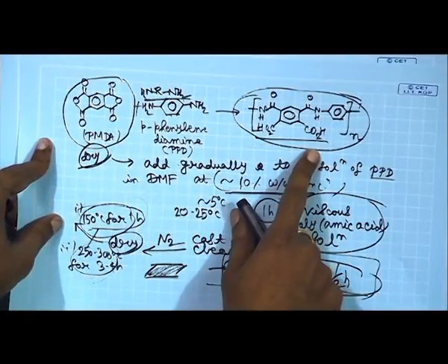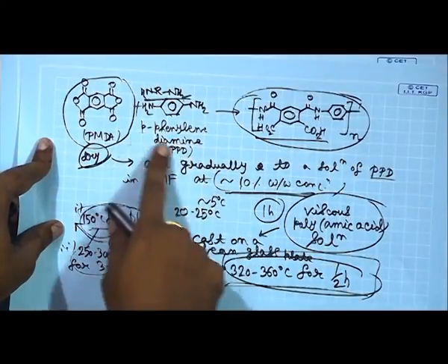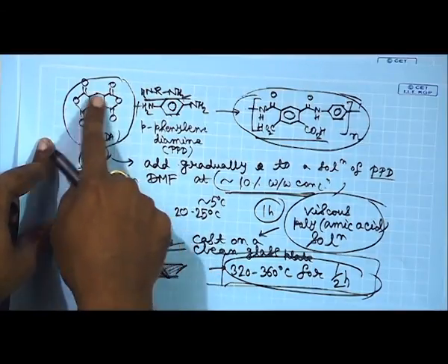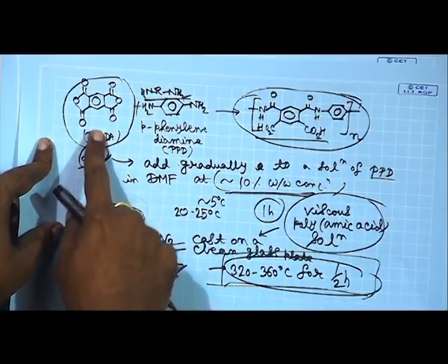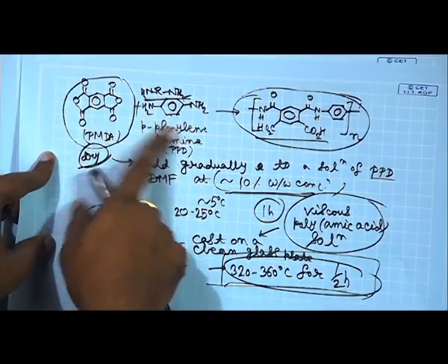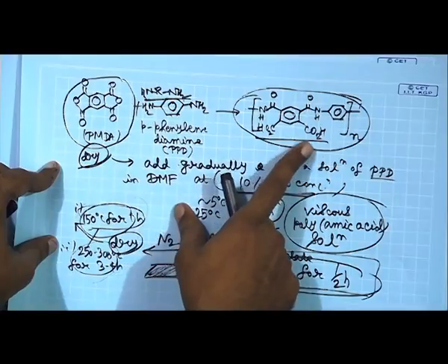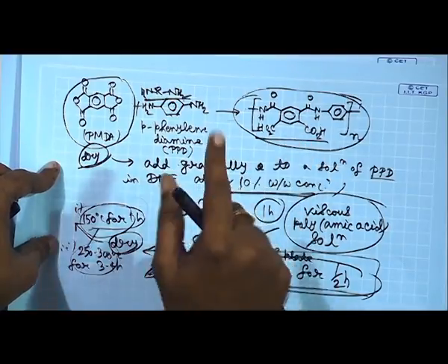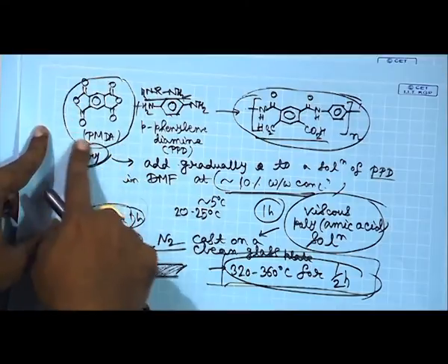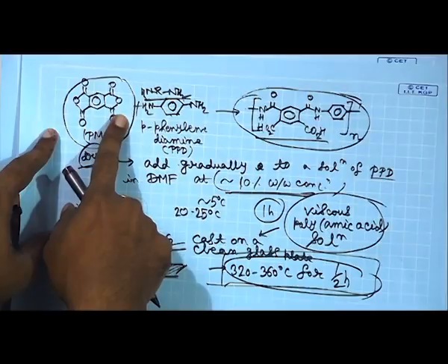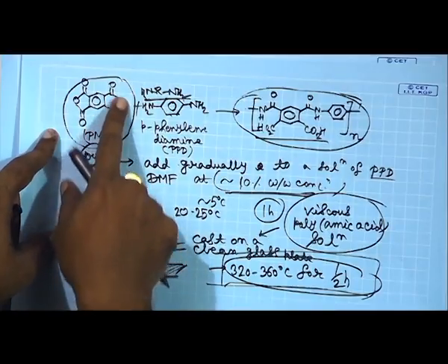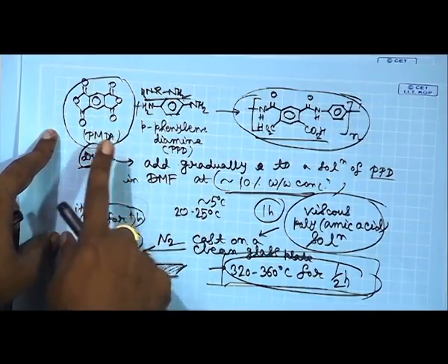I already told this before that in order to do the reaction, for this particular reaction we had explained, you start with a solution of the diamine and you add the solid, in this case pyromellitic dianhydride, to the diamine gradually. So, if you do like this, you will get very high molecular weight polymer. Why is that so? Because these aromatic dianhydrides are known to react with water. Of course, they will take water up and then they will just open this up. So, they can react with water.